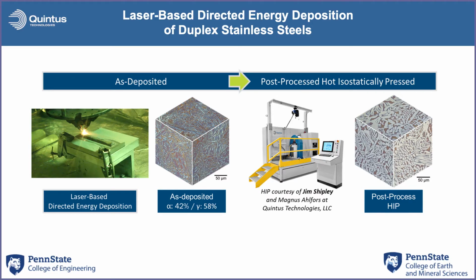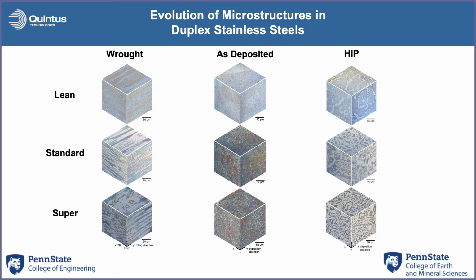We moved on from there into Inconel 625, a range of different duplex stainless steels, looking at not so much how the hot isostatic pressing process impacted the mechanical properties, but a little more in how they were impacting microstructural evolution and how we could maybe use the process to control the microstructures that we were forming. And so that worked our way even into precipitation hardened stainless steels, which are a much more complex endeavor than some of the other materials.